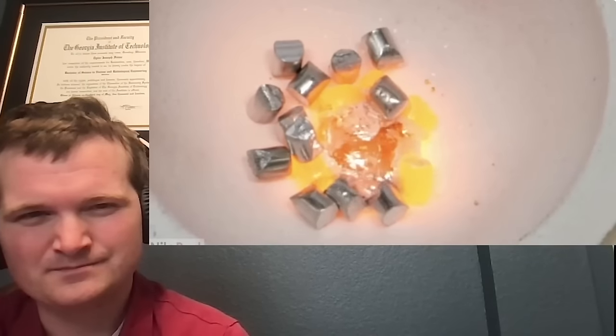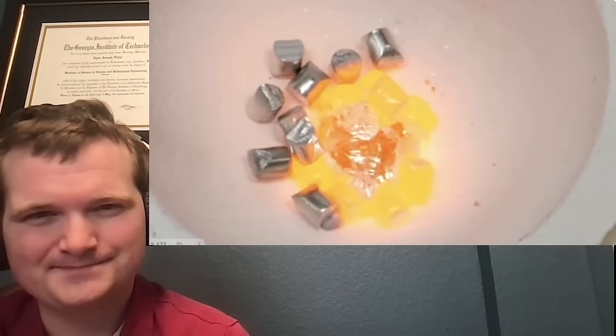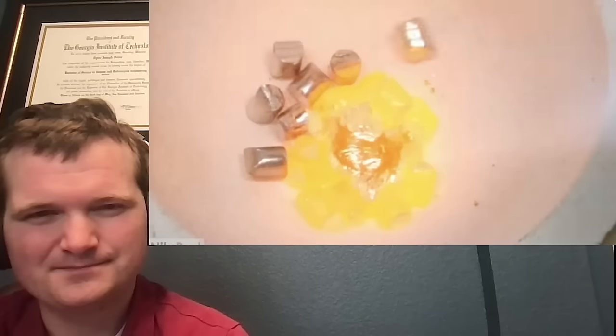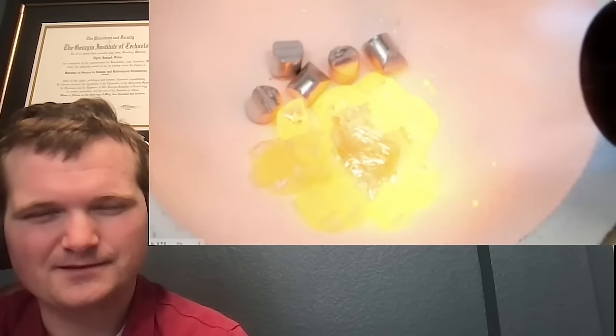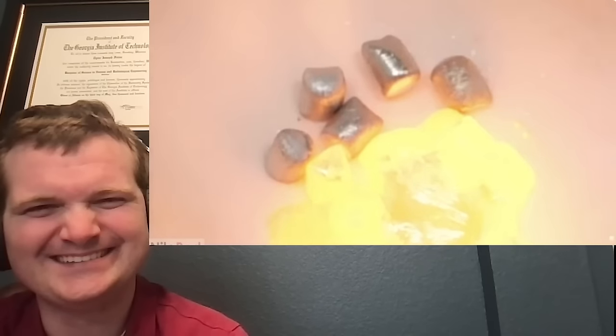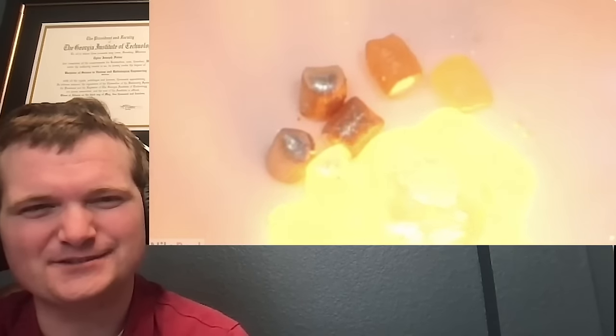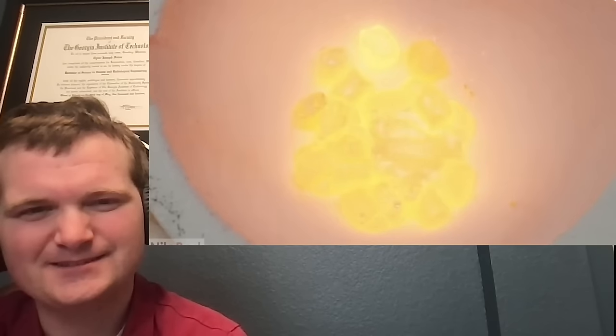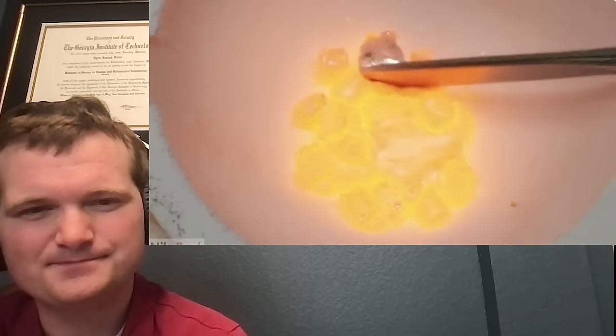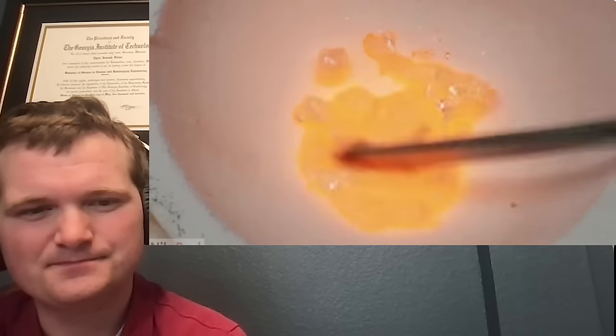The ones that were touching the gold almost immediately melted and combined with it, but it looked like the others needed a bit more convincing. Even after making them further hot, away from the heat source, they weren't melting, and this was because the thin oxide layer that naturally forms around aluminum was holding in the liquid metal. So to actually get it to mix, I was going to have to poke at it a bit, and I was happy to see that it all easily combined together.